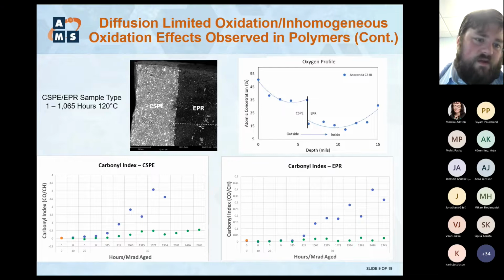So the left is the Hypalon data we've taken. The blue data represents the type 1 insulation, so the bare materials. The green data represents the type 2 data taken for the Hypalon exterior layer. And so you can see how different the oxidation rate, essentially, or the carbonyl index value, is changing over time in the two different sample types.